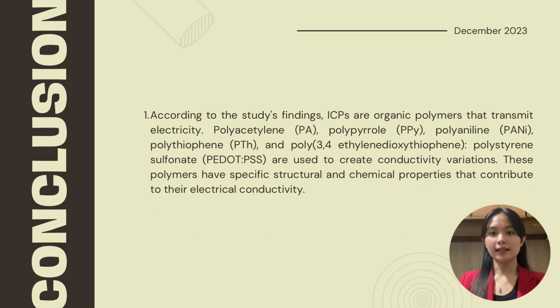Conclusion 1. The study highlights that conductive polymers, including polyacetylene, polyaniline, polythiophene, and polyethylene dioxythiophene polystyrene sulfonate, exhibit unique structural and chemical properties influencing their electrical conductivity. Despite challenges like low stability and restricted solubility, polyacetylene and polyaniline demonstrate high conductivity, while PEDOT:PSS emerges as the most successful conductive polymer, offering high conductivity and biocompatibility, making it particularly significant for flexible and wearable electronics.